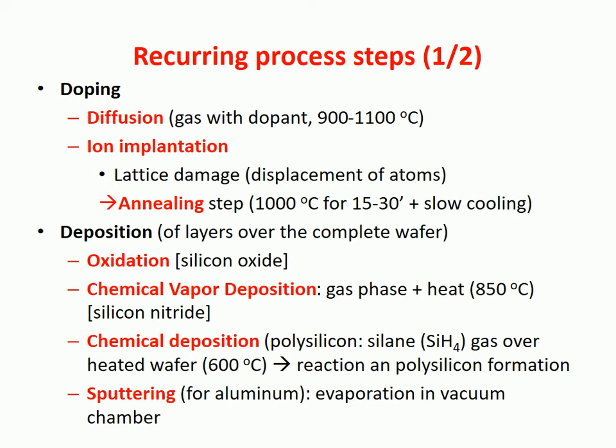Regarding doping, we have two different types of doping. We have one process that is called diffusion. Basically, we put the wafer in an oven, in the presence of some gas with dopants at a very high temperature, between 900 and more than 1000 degrees. And what happens is that the dopants penetrate into the silicon layer and diffuse in it. So this is the reason why the process is called diffusion. We need to put everything at a very high temperature in order